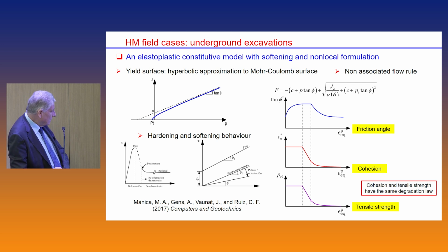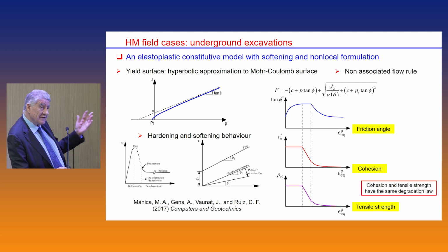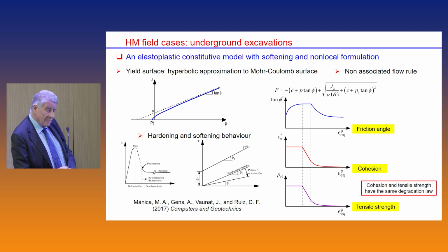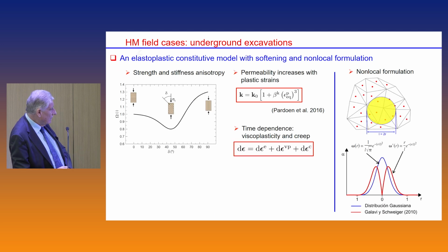This is work that was done especially by Manica. This is a rather simplistic constitutive model, but with a number of added features which make it quite useful. So we have this hyperbolic Mohr-Coulomb surface as the main yield surface, but hardening and softening is actually established by the variation of the friction angle, cohesion, asymptotic cohesion, and tensile strength. Obviously, the degradation of cohesion is much faster than the friction angle to keep into account this two-stage brittleness model that we were seeing before. Also, the strength is anisotropic, and this is the one we are going to use in the results I'm going to show.